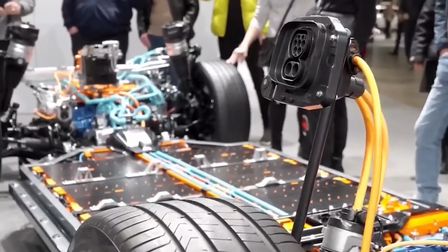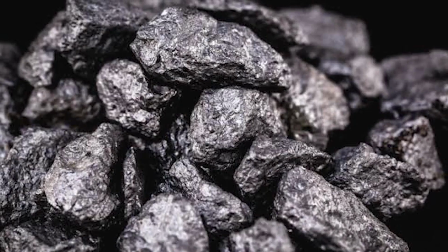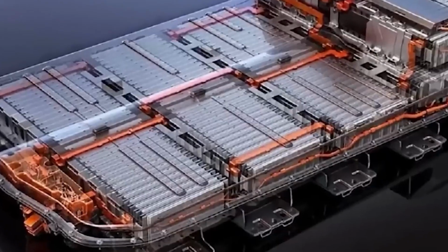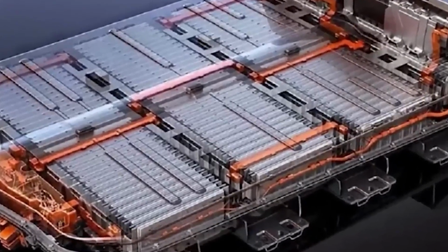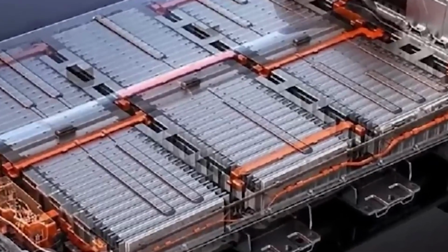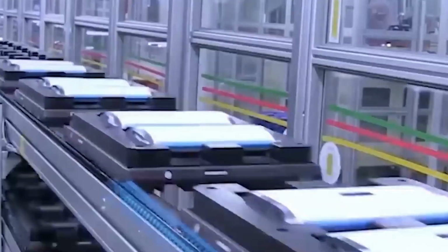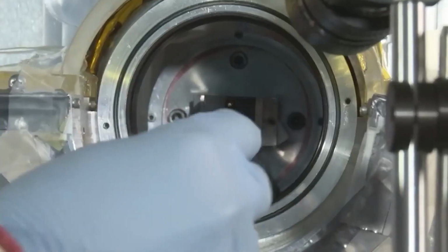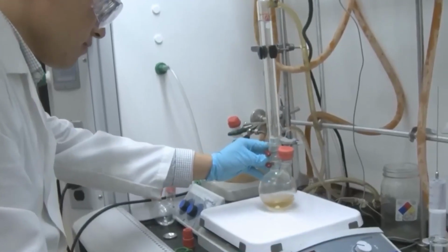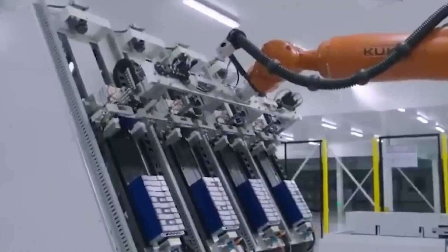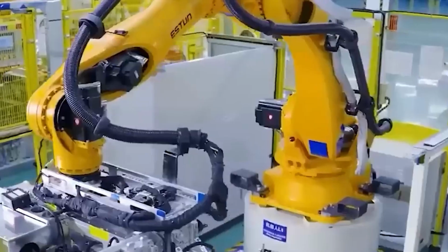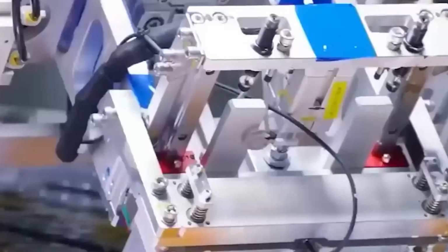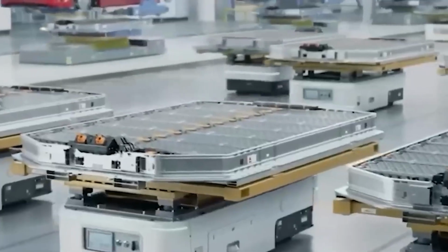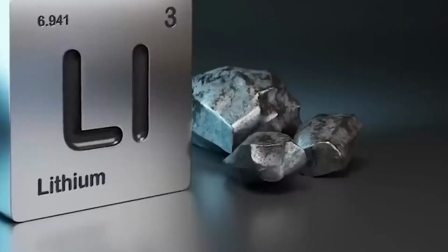7 years after niobium tungsten oxide entered the literature, one number still had not moved. Sub 1 minute charging. Full, usable charging, not a partial trickle in a lab format coin cell, remained locked out of reach. The reason had nothing to do with the material's chemistry and everything to do with what nobody could see. Researchers understood that lithium ions were bottlenecking somewhere inside these crystals. They just did not know where or why. Push the charging rate high enough, and even niobium tungsten oxide started refusing ions at the door, unless you were only asking for a small slice of the full charge. For an industry chasing gasoline speed refueling, that unexplained wall was the entire ballgame.